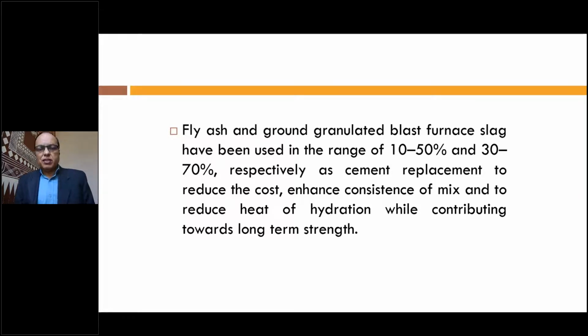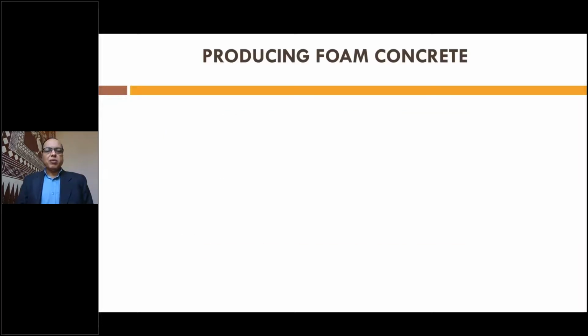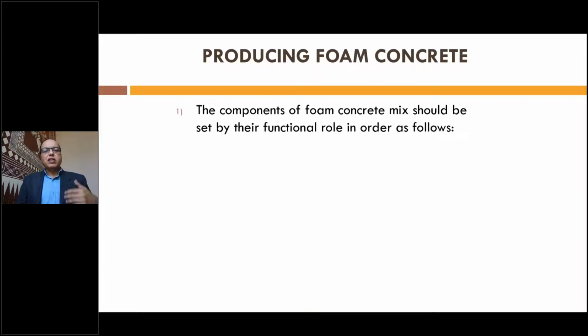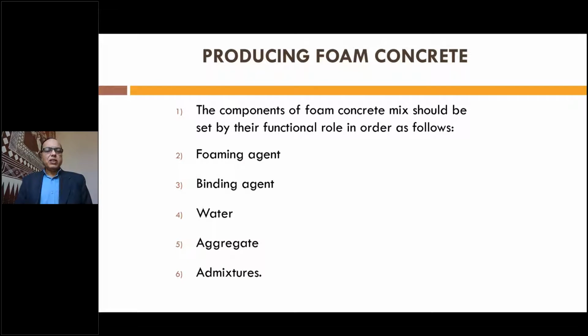If you make it 50%, it is called high volume fly ash concrete. And slag, you can make it 30 to 70%. You can go for a higher replacement of slag, up to 70%. The advantage is that the heat of hydration of that particular cement is much less because of supplementary cementitious materials, and the strength is not compromised at all. Now, in addition to this, we add a foam. We use a foaming agent, and this foaming agent is an aluminum compound or a bio compound, and this is mixed with the normal cement, water, and aggregates.